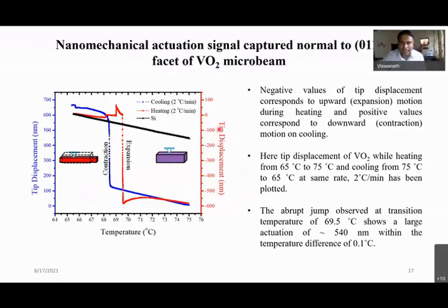So during heating, we have an expansion, and during cooling, the contraction takes place. We're again able to capture the tip displacement. But the tip displacement is not the same in terms of magnitude. I would say the expansion is more accurate, because when the crystal is expanding, it is going to push the tip up. The contact is always intact. But during the cooling, when the contraction takes place, there is a chance that the crystal may be disengaged from the tip. Right? There is a possibility of some error involved here. That is the reason we are seeing a slight difference in the magnitude of the displacement measured during expansion and contraction.